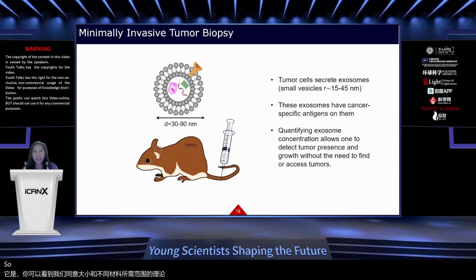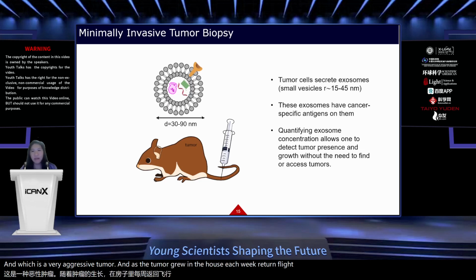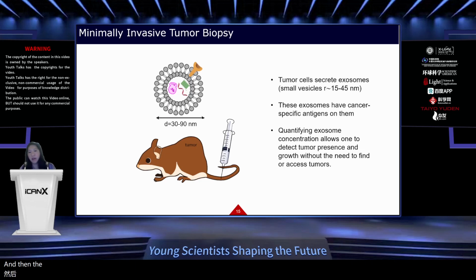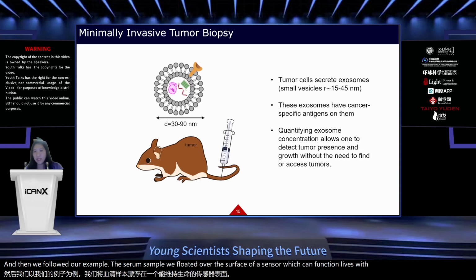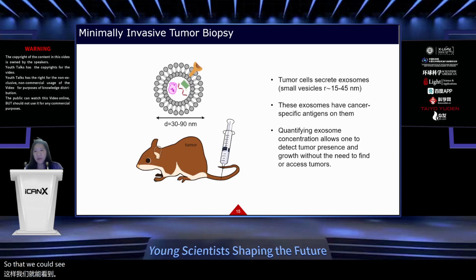So cancer detection. So we then took this to mice. So we had mice that were implanted with human Burkitt's tumor lymphoma cells, which is a very aggressive tumor. And as the tumor grew in the mouse each week, we took blood from the tail vein of the mouse and we froze it down. And then we flowed our sample, the serum sample, over the surface of our sensor, which was functionalized with antibodies, so that we could see, can we track tumor progression by the binding of these exosomes to the surface of our sensor.